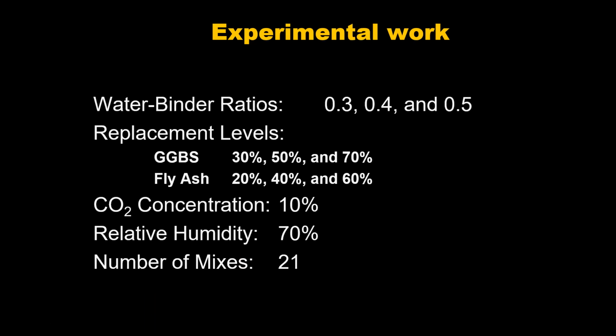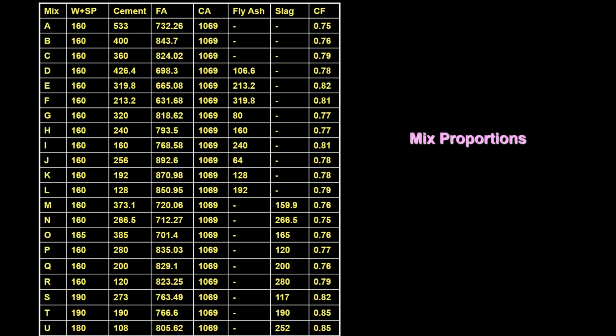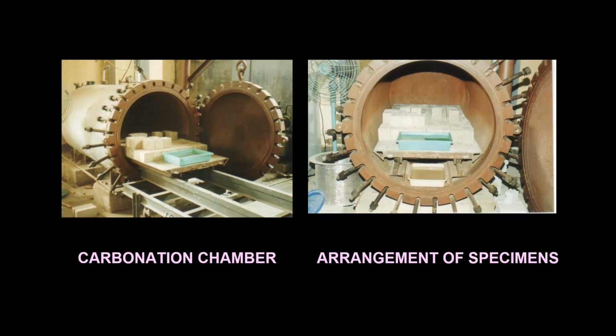So what we did, we have taken 3 different water binder ratios, 0.3, 0.4, 0.5, and for each water binder ratio, we have taken 3 different percentages of GGBS and fly ash, and it was an accelerated test. We have taken a closed chamber. In this chamber, we maintained 10% carbon dioxide and 70% relative humidity. And these are the mix proportions we have used. We exposed the concrete specimens up to 1 year, and in between we took out some specimens and measured the carbonation.